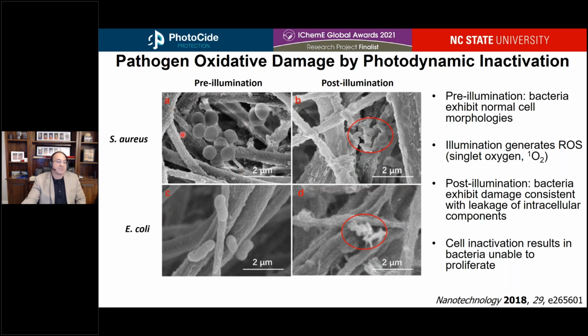Here, prior to shining visible light on our photodynamic coatings, the Staph aureus and E. coli, as examples of gram-positive and gram-negative bacteria respectively, appear to have normal, healthy cell morphologies. However, after the photodynamic process occurs, where light is used with our photosensitizers on these fibers to create reactive oxygen species, those reactive oxygen species, such as singlet oxygen, give rise to the oxidative damage that you're seeing here, and the bacteria exhibit damage consistent with the leakage of intracellular components, leading to their inactivation. They're unable to proliferate, unable to be transmitted or infect new hosts. So again, extensive oxidative damage leads to bacterial inactivation.